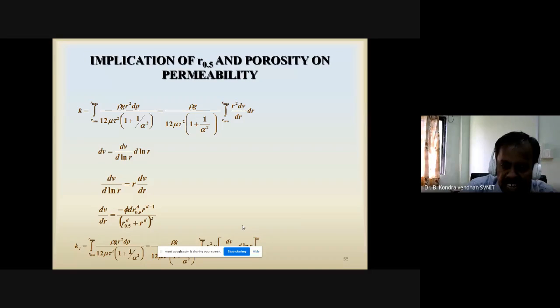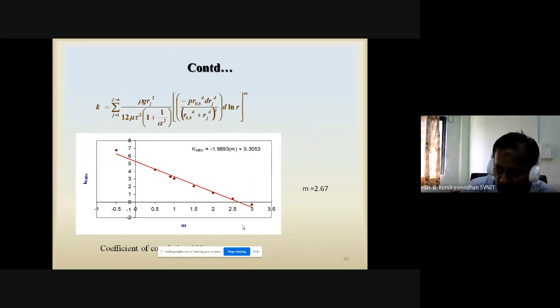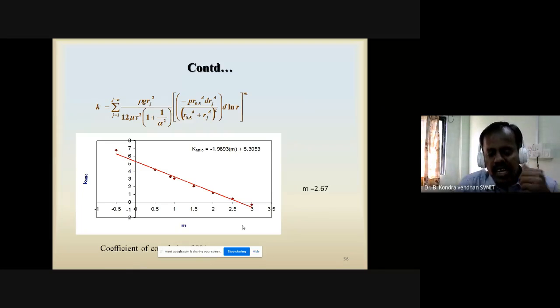That is called the interconnectivity factor. For that, we have done some innovative procedure. We have taken a number of literature permeability values and the corresponding water cement ratio and curing ages. We have calculated the permeability through our estimated formula, and we have taken the ratio between our experimental value and our estimated value.